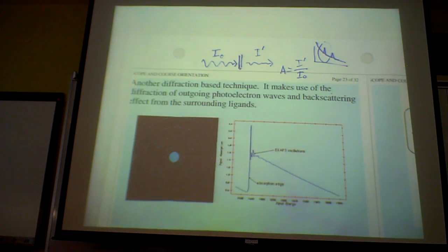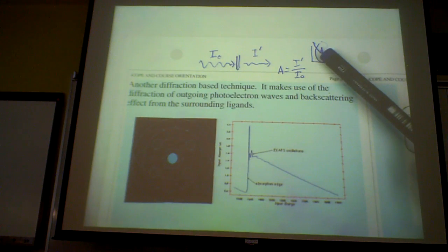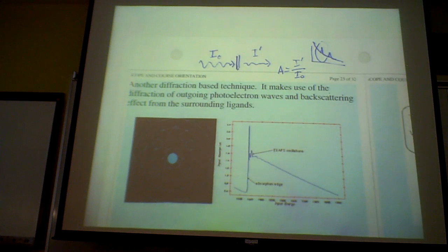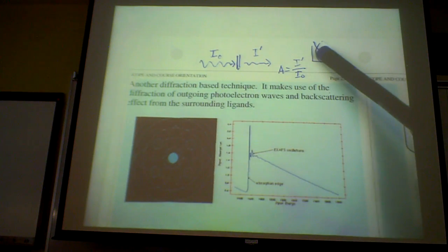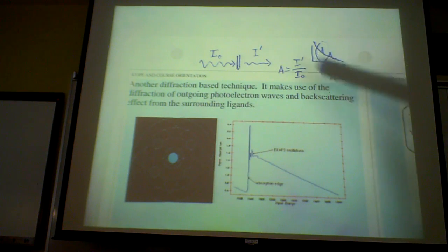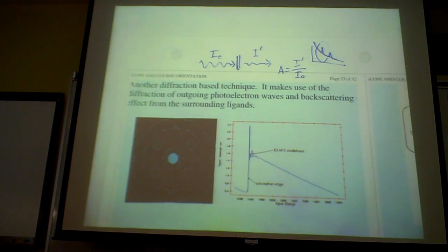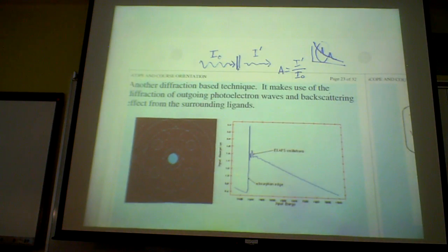And this absorption edge, of course, is very useful because it contains electronic structure information, because when you hit the material just right, the material absorbs the photon and excites an electron to an upper state, and this is why you see a bump like this. Exactly like your UV absorption spectroscopy, you see peaks corresponding to electronic excitation of the material.